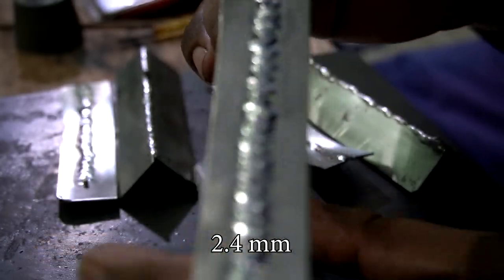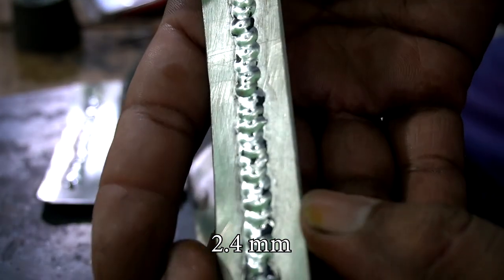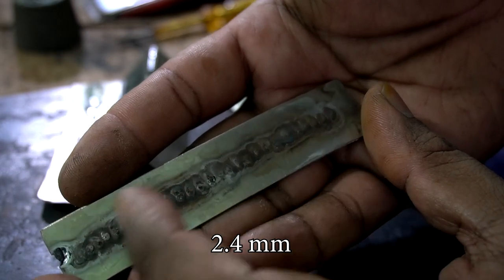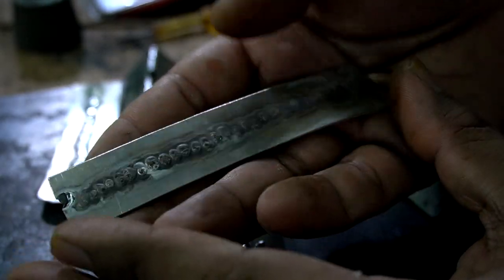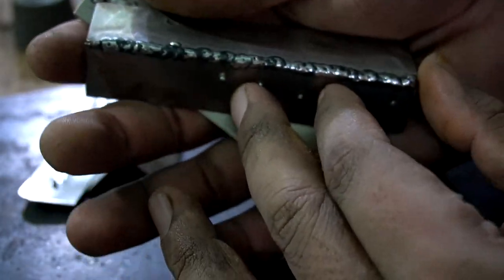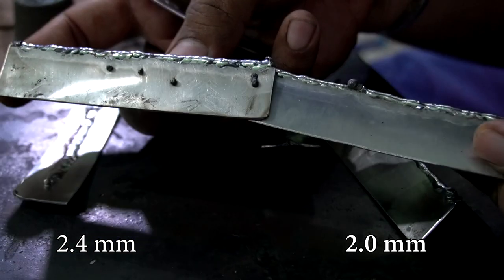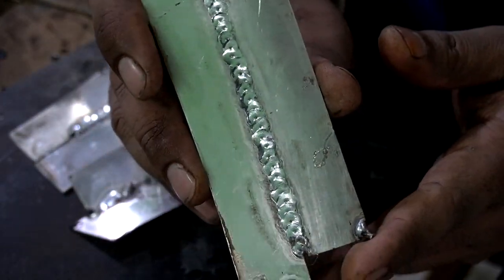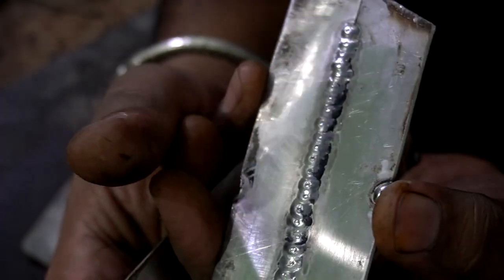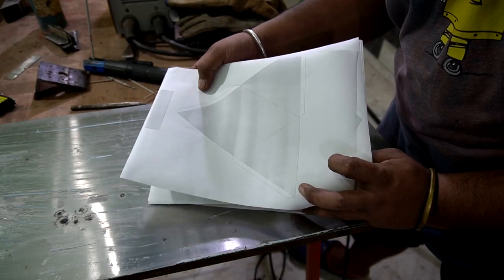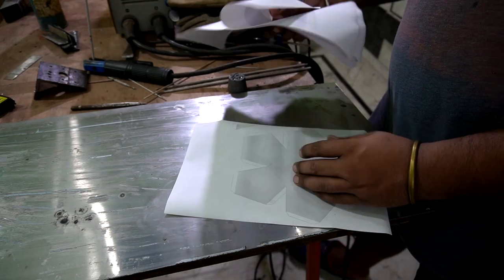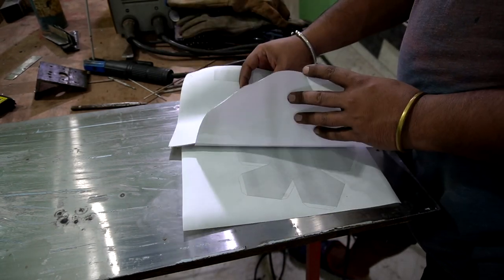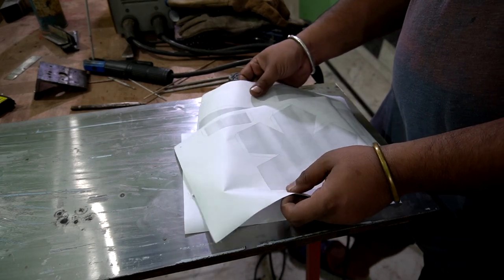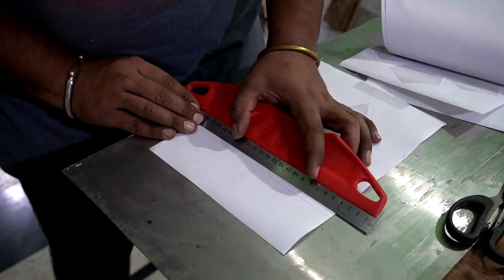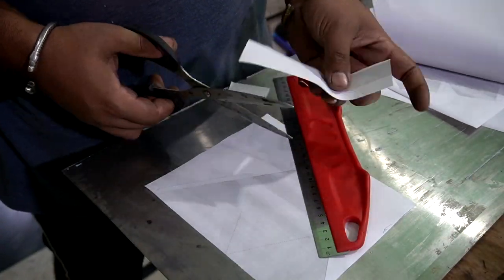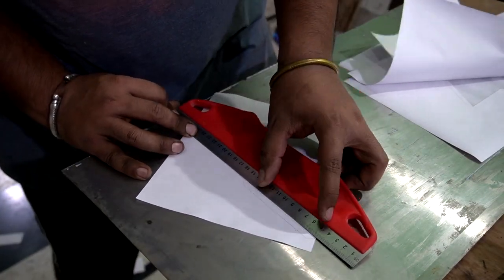So this result I got with a 2.4 millimeter electrode, and as you can see the weld bead is quite wide and penetrates a lot into the metal, and the weld bead is quite thick compared to the 2 millimeter welding electrode. So to give you a much better idea, now I'm going to make some polyhedrons, and that will show which welding electrode seems feasible. And if you want to make these shapes, you can download the PDF file from the description section.